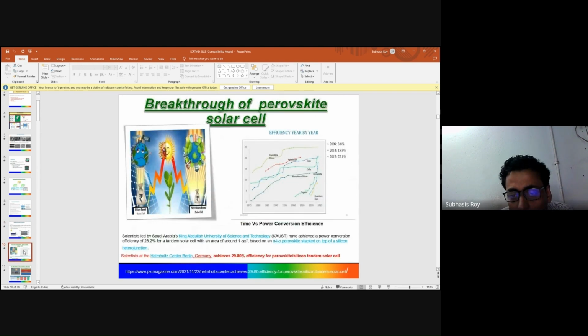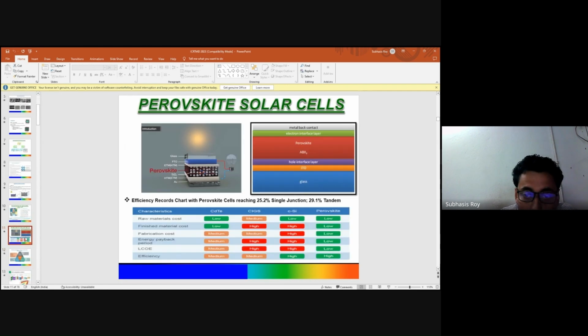If you see the trend in the perovskite materials in the applications of solar cells, nowadays the trend, compared with the others like crystalline, polycrystalline, and other materials, is that perovskite application has dramatically increased, and it has reached an efficiency of around 28.2%. Currently, it is reported in tandem solar cells by King Abdullah University in Saudi Arabia. Why has it increased? Because of the easy fabrication process, the easily tunable process, its much higher absorption coefficient, and we can tune the band gap property very easily.